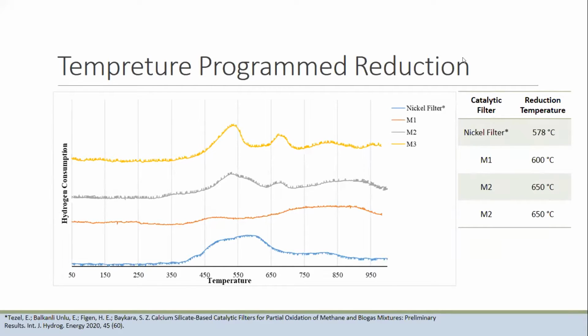According to that, increasing the molybdenum ratio in the mixed oxide increased the clarity of the peaks and the final selected temperature. Reduction temperatures were selected respectively for the M1 catalyst 600 degrees, for M2 650 degrees, also for M3 650 degrees. All catalysts were treated with the reduction condition before being tested for the catalytic partial oxidation reaction.